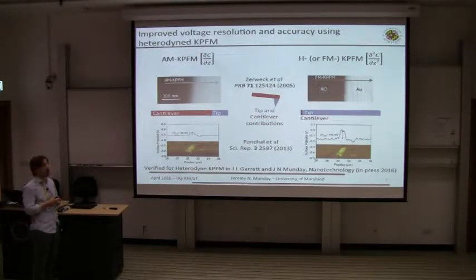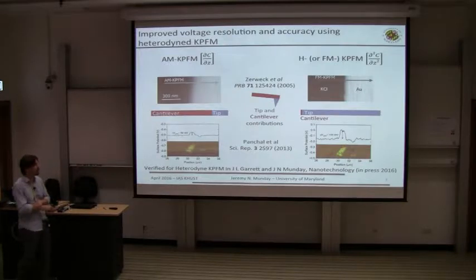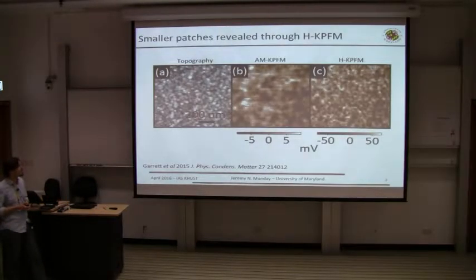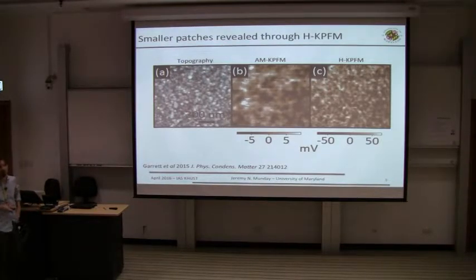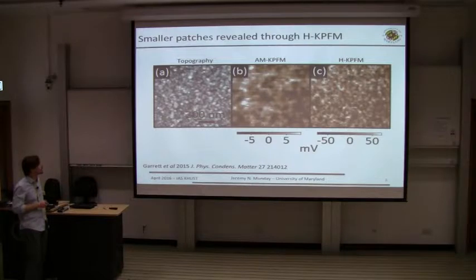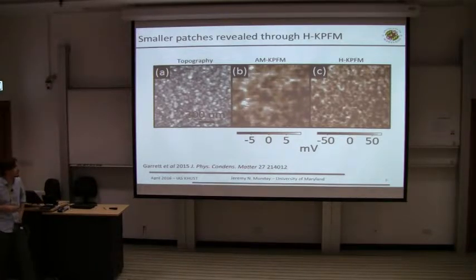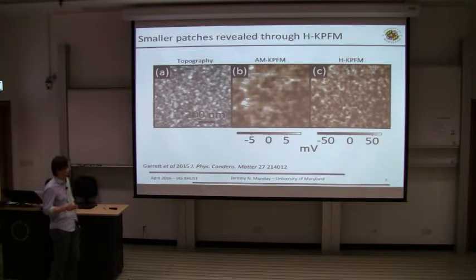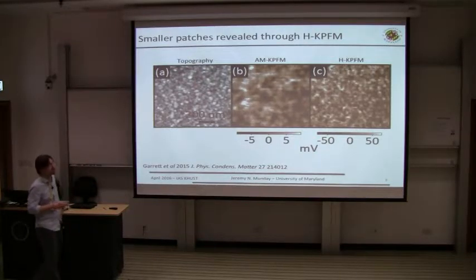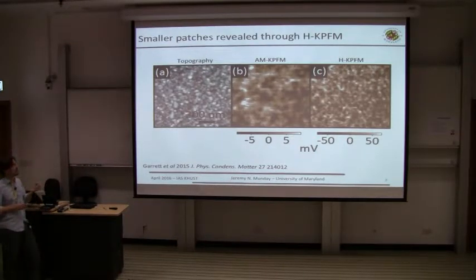So when we're deciding what to look at for our samples, we decided to go with one of these sorts of methods for these reasons. So here's an example of some samples that we were using. These are gold samples that were deposited by electron beam evaporation. And so here we have topography. Here's some amplitude modulated KPFM, and then the heterodyne KPFM. And you can see that you start to reveal smaller features in this sort of method. And you can also see that you're revealing larger potential variation that you get as well. Again, because you're really looking at the interaction between the tip and the sample rather than a combination of tip and cantilever.